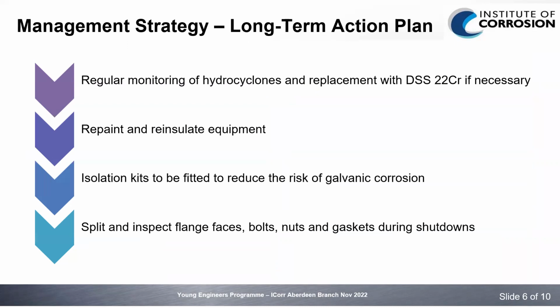A few of the long-term plans that we've got: 2 of the hydrocyclones have been replaced with duplex due to CO2 corrosion because there was breakdown of the coating. Once we've monitored the hydrocyclones for a while, we would like to potentially implement duplex throughout the hydrocyclones if it's required, dependent on the inspection results.